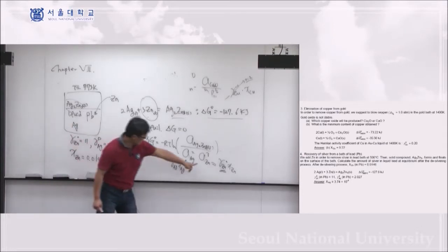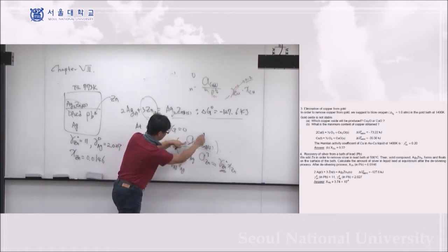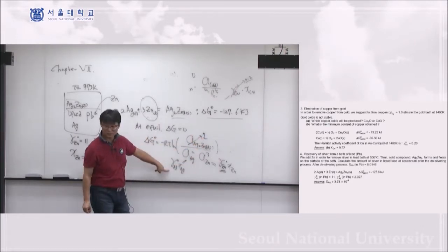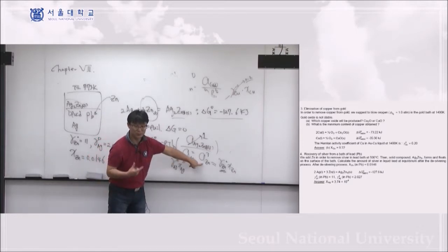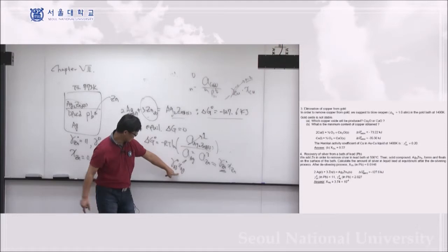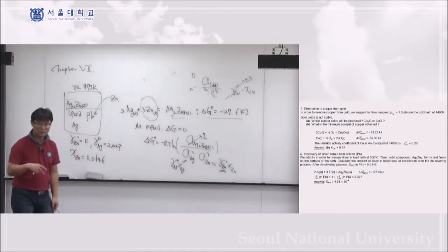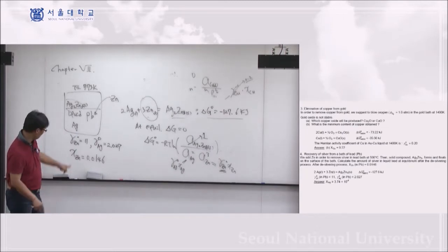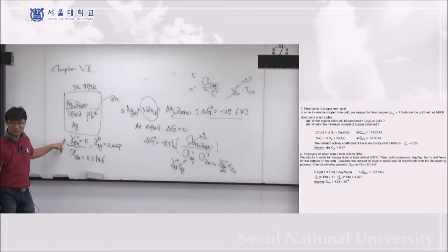So when you have a high activity coefficient, and this is 1, this is determined, you cannot change it. If you're adding the same amount, but the activity becomes bigger and bigger, your final content of the Ag should be smaller and smaller. You get it? So locally, for Zn, the activity coefficient is 11, even in the lead base. So it's one of the best agents you can think about.